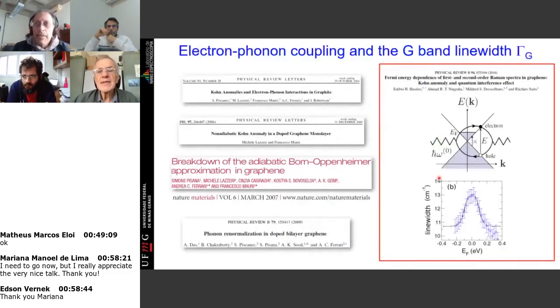And then the way people found to prove this, so all these papers that I cite here are related to this, it's Kohn anomalies in electron-phonon interaction in graphite, etc. The way they proved it was to show that when you gate dope the graphene, you change the phonon line width. So they fully demonstrated that you cannot neglect the electronic structure when looking into phonons. And the way they explained it, and we now understand, is that you can model the electron-phonon interaction by assuming that, because graphene, this is the electronic structure, it's the cone structure of graphene.